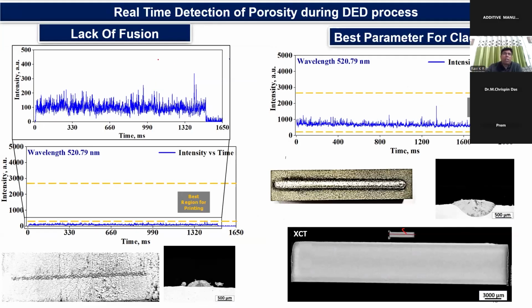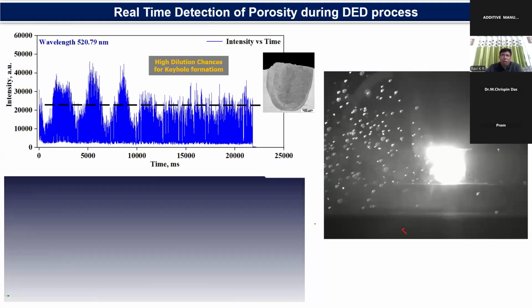When I did an experiment with a lack of fusion regime, which was identified by this particular spectrum, it was validated with the experiment. It shows lack of fusion. When I use the best parameters for the clad and use tomography, we identify there was no defect. I'll not get into the detail of this particular technique.